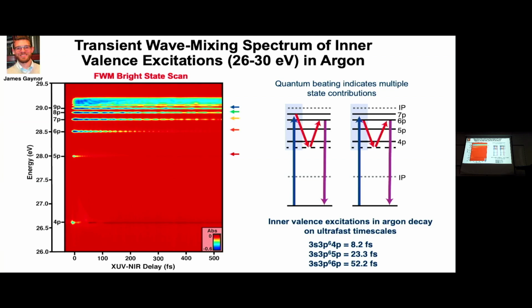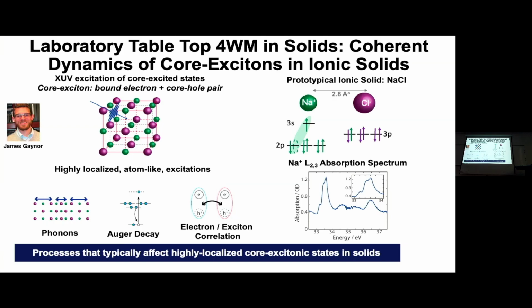So taking this lesson from the atomic work we were doing, we decided to try it in solids. In some solids, like sodium chloride, you can have very isolated sodium atoms that have normal S and P, atomic-like states. And they give rise to features in the spectrum that are very sharp and look atomic-like. So, for example, if you look at the sodium plus in sodium chloride around the L23 edge in the XUV, you see this beautiful peak, which is assigned to an almost atomic-like transition. And there are Rydberg-like kinds of features and so on.